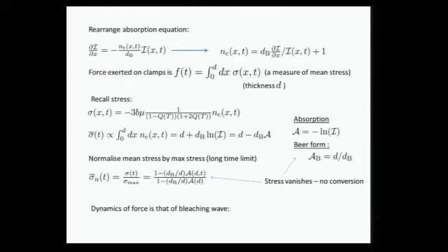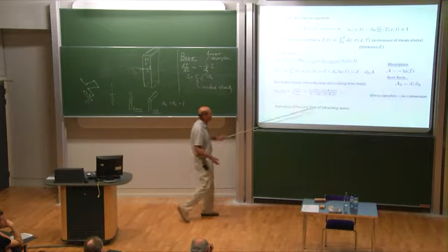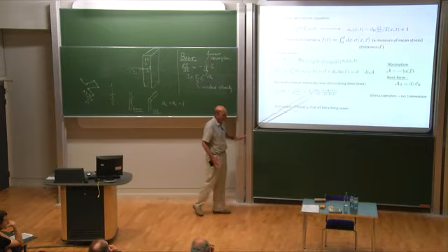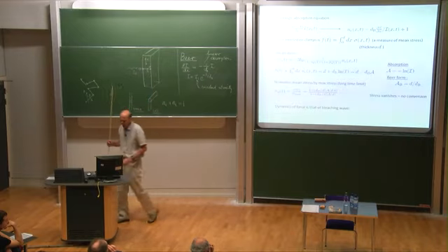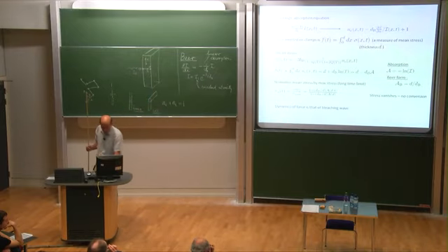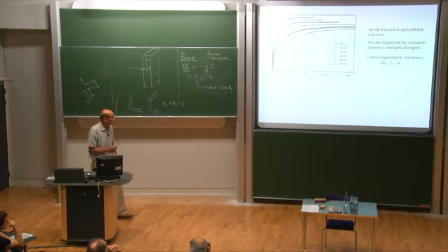And I can normalize this by its long time value, which gets rid of this nasty or involved coefficient. And I have a simple expression for the normalized stress, that is the force, as a function of time. It just depends on the buildup of the absorption divided by the long time absorption in the denominator. So the dynamics of the force is the dynamics of the bleaching wave.